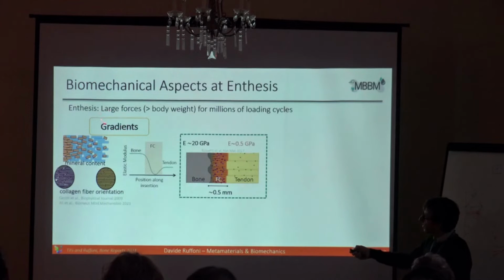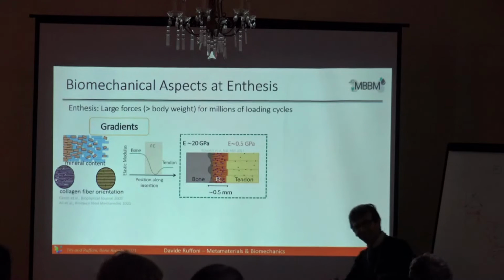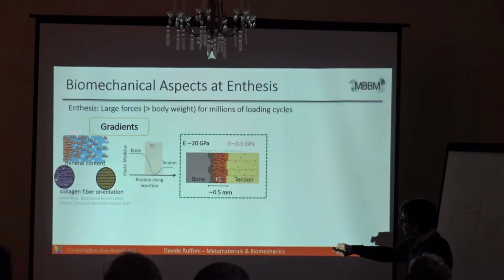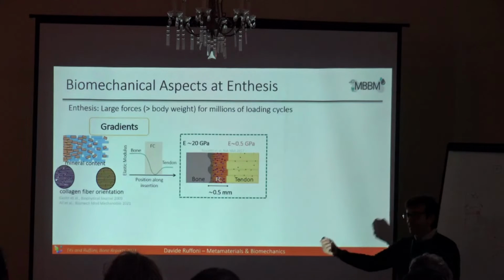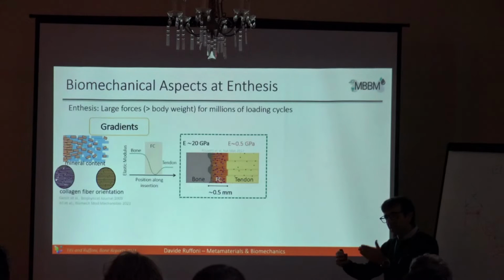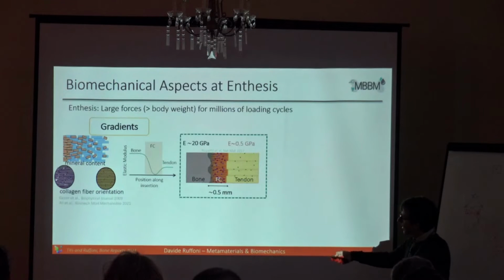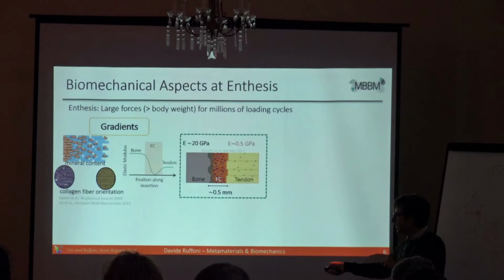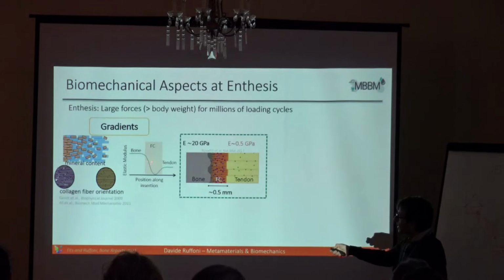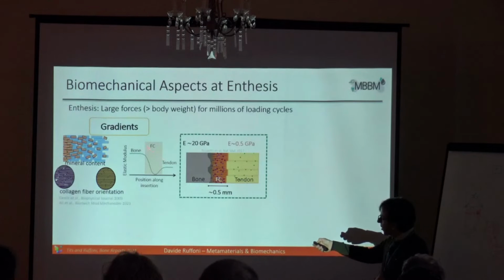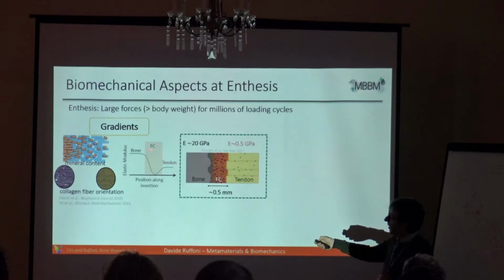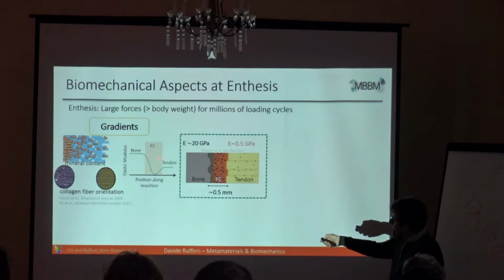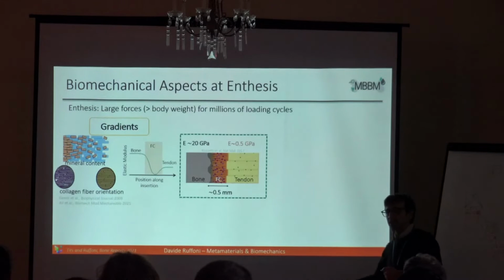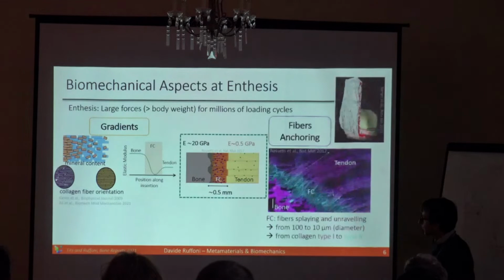For example, we know there are some gradients. Nicola also did a study on this. There are gradients in mineral content. Bone is mineralized, tendon is not mineralized. At the interface, there are gradients in mineral content, and gradients a little bit in the organization of collagen fibers. And what is interesting is that there seems to be a region which has an even lower elastic modulus than tendon, and of course lower than bone. So the attachment of bone to tendon goes through a region which is even more compliant than tendon itself. This is something that people have reported already.